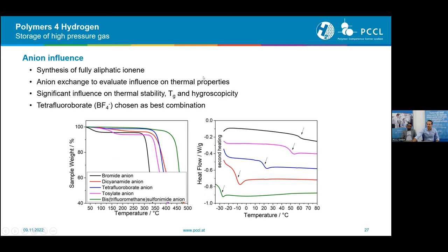And then we exchange the anion just to get an insight into the influence on the thermal properties. Here you can see the thermogravimetric analysis and the differential scanning calorimetry. You can obviously see that there is a very significant impact on the thermal stability, on the glass transition temperature, and also on the hygroscopicity. So here you can see the initial mass loss, which can be attributed to water loss.